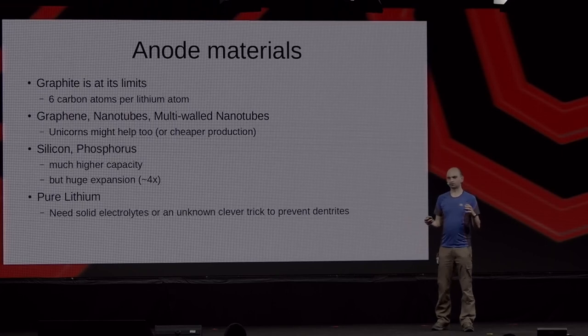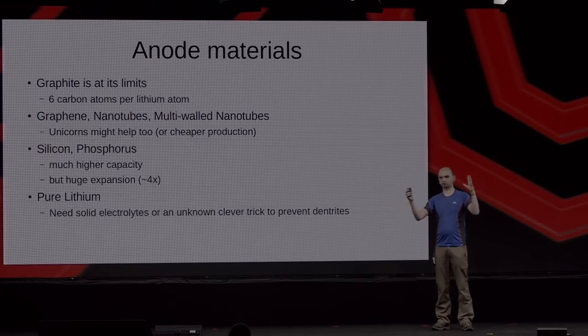The problem is when you form such an alloy, what you get is much bigger. The electrode just gets much bigger. It gets 4 times as big as it was before, and this puts a lot of stress on the material, and it starts to crack. Basically, every time you use the battery again, it destroys itself. That's not helpful. There are tricks. Some people make silicon like the wafers we use in chips, and make them very small, and you have very small structures that can store the lithium inside of them without cracking because they are very small. But they never talk about price for some reason. I don't know why. I think it might be too expensive.